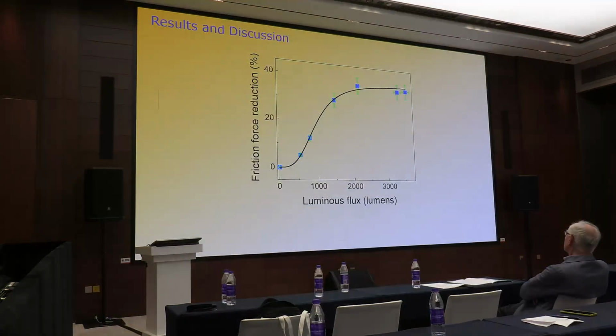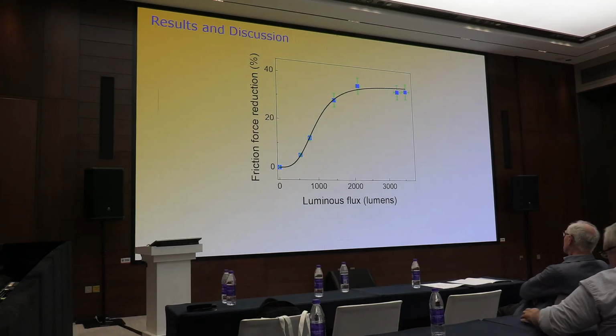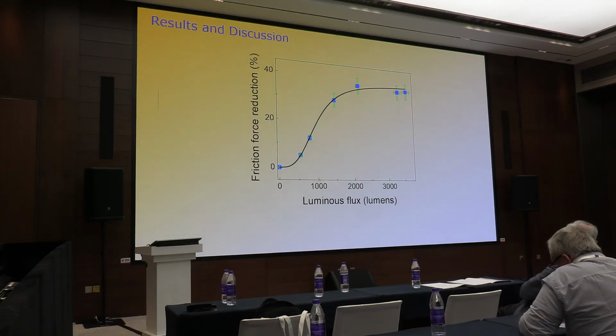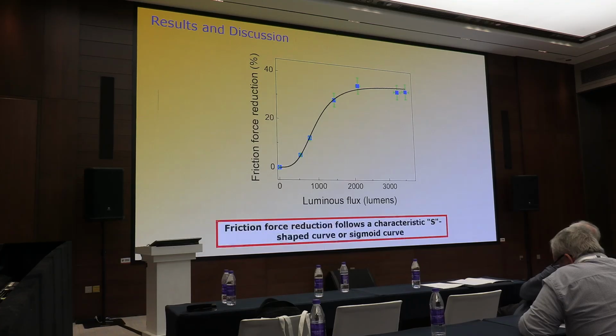Okay, we analyze this result in terms of friction force reduction. You can see that the friction force reduction is higher when we have a higher luminous flux. It's in agreement: we increase the luminous flux, we reduce the friction force more. An important point is this characteristic S-shaped, sigmoidal curve for the dependence of the reduction as a function of the luminous flux.